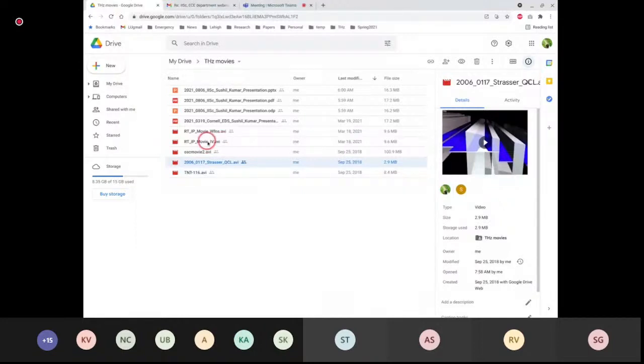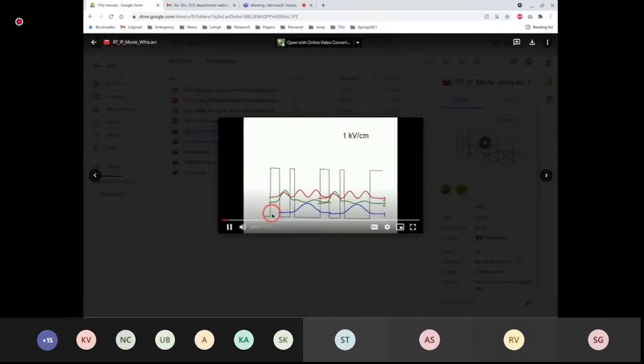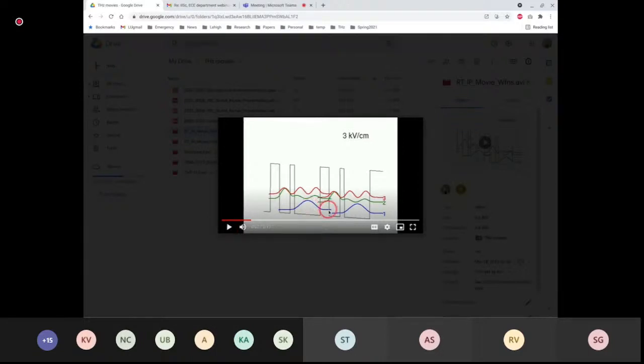I want to show you also something I generated for a very simple structure. You can see in this image, gradually the electric field across this structure is being increased. And these wiggly lines are basically the probability density of electrons in each of these three subbands. So this two-well structure is repeated. Most electrons occupy this level, but as you keep on increasing the voltage, at some point some levels align with the levels in the adjacent well, and here, for example, the blue level is aligning with 2. This is not actually good. You need to align with 3. Then they are overlapping.